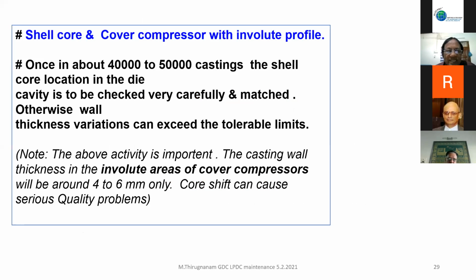Once in about 40,000 shots, the shell core location has got to be checked once again. For example, in the cover compressor castings, it's a very complicated involute profile. Generally, the wall thickness will be 4 to 6 mm with not much variation. If there's a shift, they will cut at several sections of the cover compressor. If there is a shift of more than 0.2 difference, they won't accept. I have seen thousands of castings rejected because the sand core location was not right.